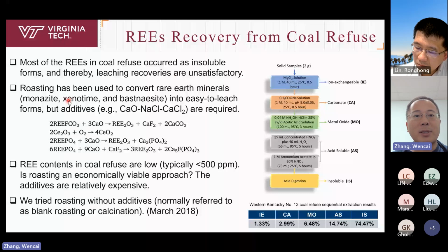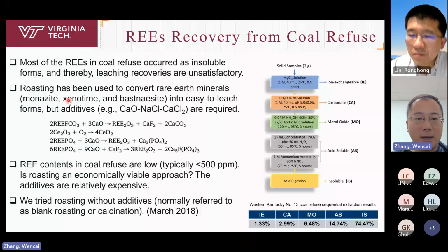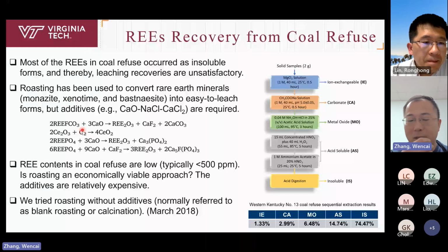Roasting is very commonly used in the rare earth industry to increase the leachability of rare earth minerals. Because we found that rare earths in the coal refuse are very difficult to leach, we tried roasting to improve their leachability from the coal refuse. But there is an issue. If you want to add additives, you need to spend money to buy them, and this will increase your recovery cost. So what we did is roast the sample at high temperature without adding any additives. This is some work we did in March of 2018. We thought it may work or it may not, but finally we found that it works well.